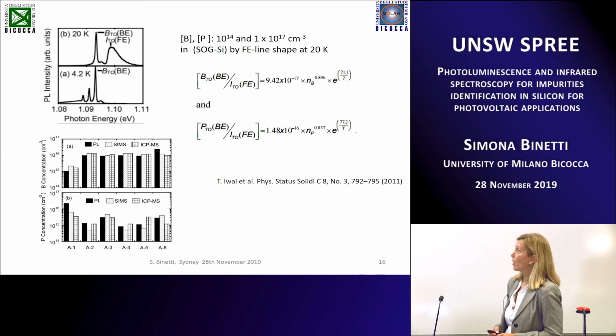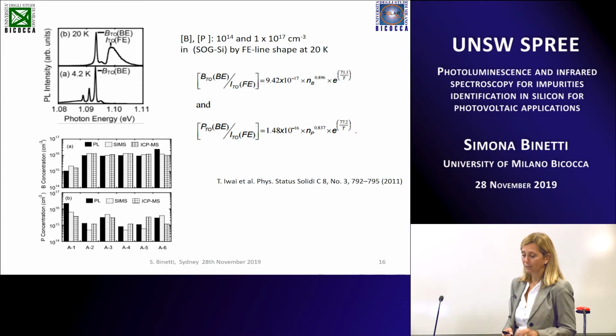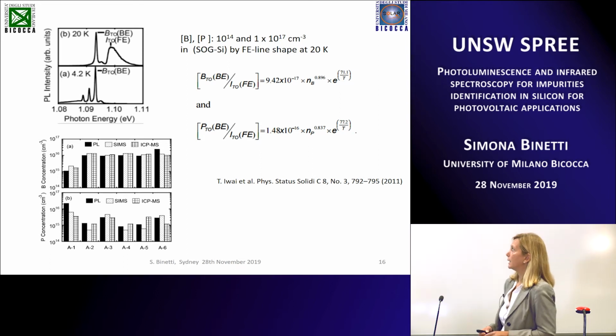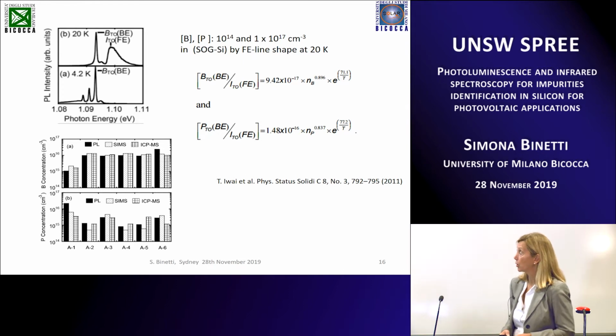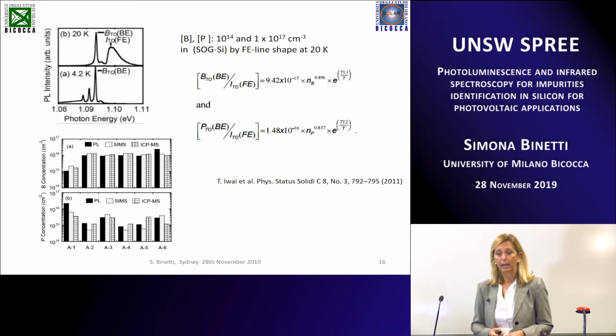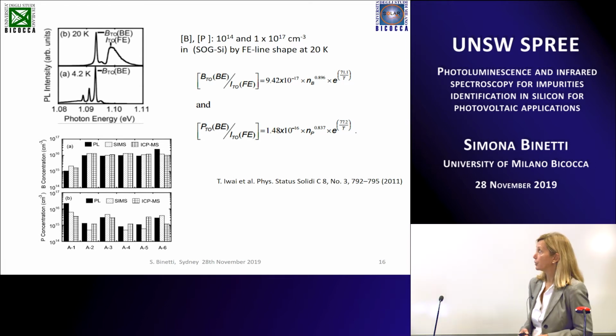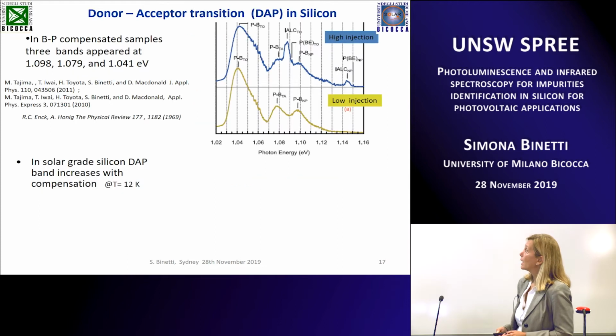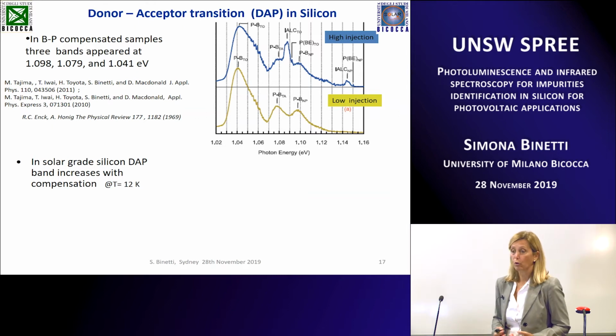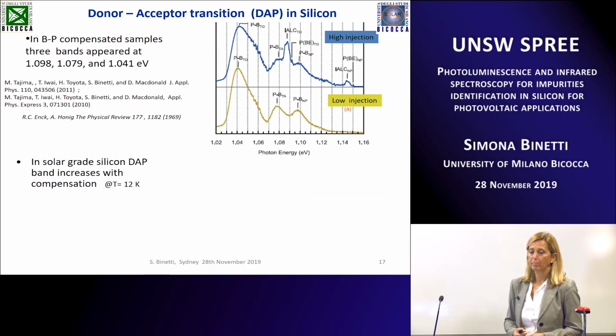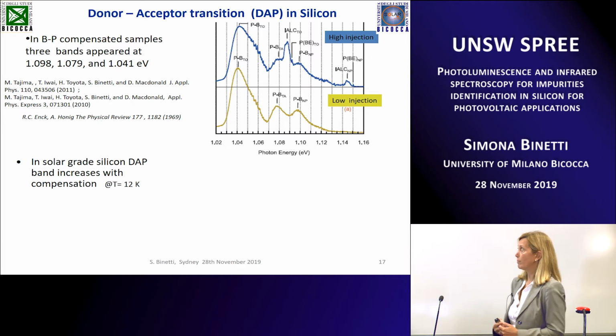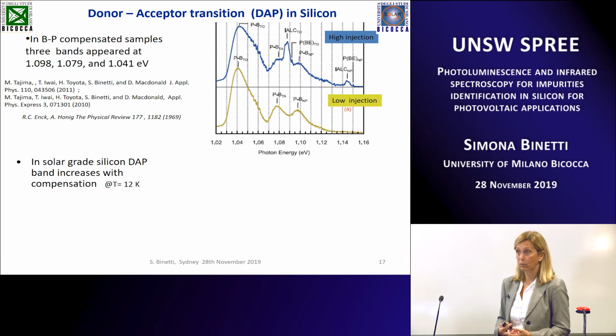And it's possible to have a very accurate quantification of dopants in your material, and a correlation has been done with much more expensive, much more time-consuming techniques like secondary ion mass spectroscopy and ICP mass spectroscopy. In silicon, you can have also donor-acceptor pairs. It's not so common, but if you have a compensated material, with a level close to the conduction band and a level closer to the valence band, you can detect the donor-acceptor transition.